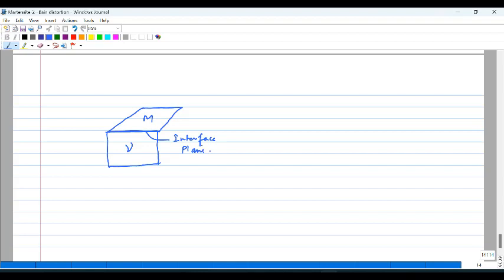That's the interface plane or the habit plane. So this is a displacive transformation which is occurring here. We have already discussed it. And if this is unconstrained, if there is no constraint given by the surrounding matrix that you have around this plate of Martensite which is forming, then the interface plane is going to remain like this. It is going to remain flat. Okay.